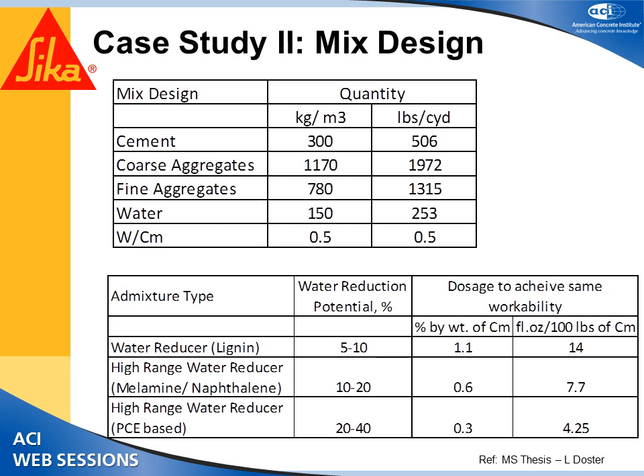Now someone would say that this was possible also using any other water reducing admixture, not only PCE based. So what is the big thing about the PCE? So I refer to one case study which was done by a student for his master's thesis at SICA. What he had done is basically he had selected a mix design which has a cement content of 506 and 0.5 water cement ratio. And he selected 3 different kinds of admixtures of different bases. The first one was lignin based, the second one was melamine naphthalene, and the third one was PCE based. All these 3 admixtures were 40% solid products, and he added them to get the same workability. So the mix design was the same.